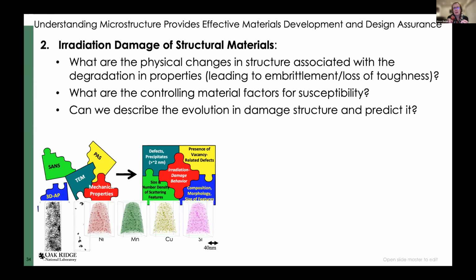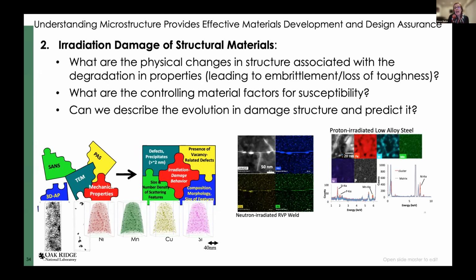We need to know what's going on compositionally, and for a long time that was only attainable by atom probe field ion microscopy. And now, as techniques have improved, we are still concerned with defects, any precipitation that might occur. We're interested in vacancy-related damage, and we want a bulk measure. So techniques, well, TEM, atom probe tomography, small angle neutron scattering, and positron annihilation all have a role to play, along with mechanical properties. And the new techniques that we've got now are even rivaling the atom probe.